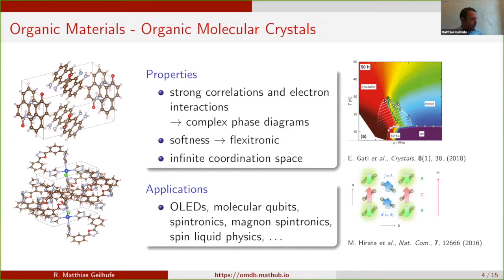If you calculate the band structure of these materials, you will see that the bandwidth is smaller compared to inorganic materials by at least an order of 10, or sometimes even 2 orders of magnitude. And as we can relate the flatness of the bands to a very tiny kinetic energy of the quasi-particle excitations, any interaction which takes place between quasi-particles becomes dominant. And this typically leads to very, very rich phase diagrams of the organics, which show all sorts of many-body instabilities into superconductors, or metal insulator transitions into the magnetic phases.